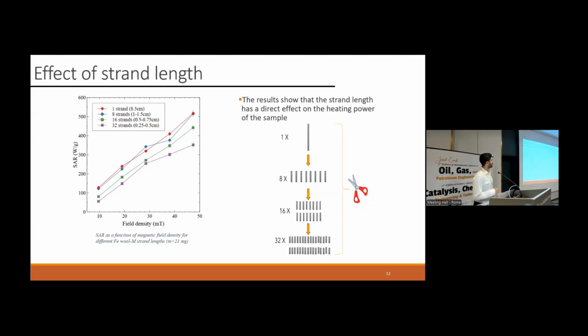The second thing that we studied was the effect of the strand length. And to study this, we took one really long strand, it was around 8.5 centimeters. We did the calorimetric measurements. And then we cut it into 8 smaller pieces, 16, and then finally 32. And what we observed is that when we went down with the strand length, the heating was also affected, and it also got lower.